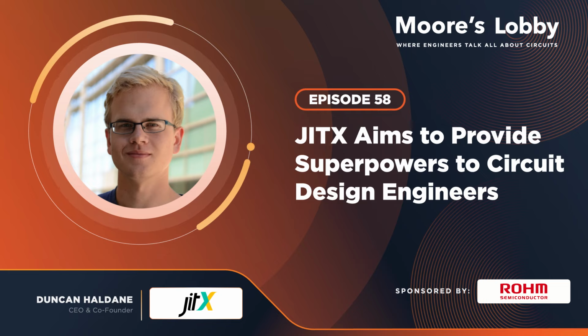Silicon carbide devices are a type of wide bandgap semiconductor, and the difference compared to silicon is that it has a much higher dielectric breakdown. This allows silicon carbide devices to be made smaller, yet have lower on resistance, and still be capable of operating at very high voltages. In addition, silicon carbide devices have much lower reverse recovery charge, which results in lower switching losses.